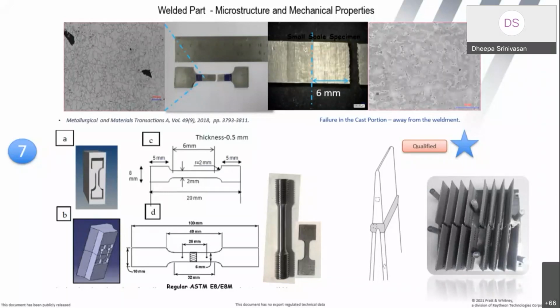Why? Because the true development of a part like this, like a cylinder and then machining out dog bone specimens, may not be representative of the process parameter optimization that I spoke of in challenge 1, vis-a-vis the actual part geometry like this. So there may be large variations, and that is truly a challenge we are facing in small scale testing. ASTM and several of the committees have taken this up in a big way. Small scale mechanical testing is very, very imperative to develop and establish in the next 10 years, in order to truly qualify, and qualify in an accelerated manner, additive manufacturing.